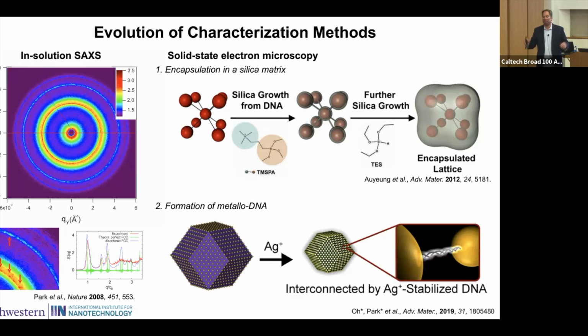You can actually burn out the oligonucleotides after the fact, and you can then use the captured lattice for all sorts of different purposes. We've generated catalysts that way. We've recently figured out there are ways to get rid of the silica. You don't need to use silica in certain cases. You can use, for example, silver ions, which will intercalate into DNA between the bases. Intercalation is a bad term. It's actually coordination chemistry in this case. It locks the oligonucleotides into place and takes these from low temperature materials to relatively high temperature materials, things you can boil and they won't come apart.